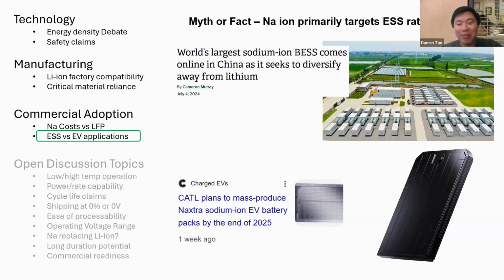It doesn't have a stable phase. So if you make sodium iron phosphate and you try to cycle it, you'll see 2 plateaus, not 1. So it undergoes a phase transition and it's not stable. So what innovators do is they remove a couple of moles of oxygen and the structure transforms from the olivine structure into the Nasicon structure, and that's where you get sodium iron pyrophosphate. That's the stable version of it.